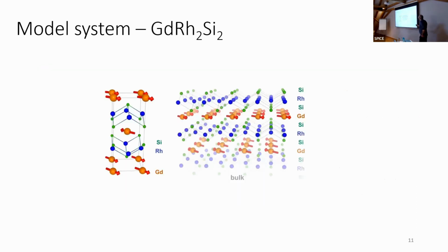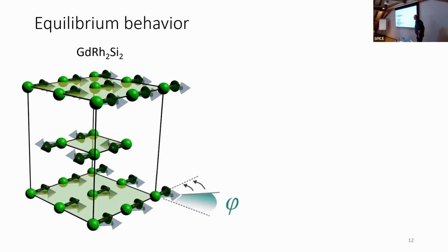And I'm just going to try to skip to the essence of things, which are most relevant for everybody anyway. So we have our little model system. This is our model system, gadolinium, rhodium, 2 silicon 2. It's an antiferromagnet with ferromagnetic layers of gadolinium. They're antiferromagnetically coupled to each other. And there's these layers of silicon and rhodium in between, which are not going to serve any purpose for what I want to say now. So I'm just not going to even draw them anymore, as you can see here. Same material, rhodium and silicon, and we have these layers.